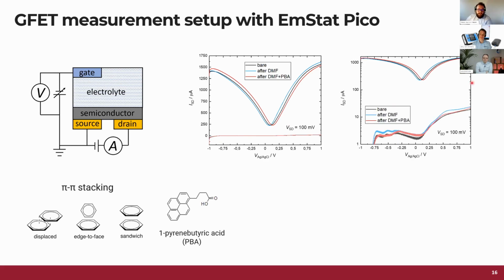We can also show this on a logarithmic scale graph like this. Those are our source drain current here on the top, and those in here are the leakage current. Despite the fact there is no passivation of electrodes whatsoever, the gold electrodes were not passivated with the SU8, they do not exhibit that much leakage current. It is at least 100 times lower than the actual source drain current stemming from the electron and hole transfer in the graphene sheet itself.